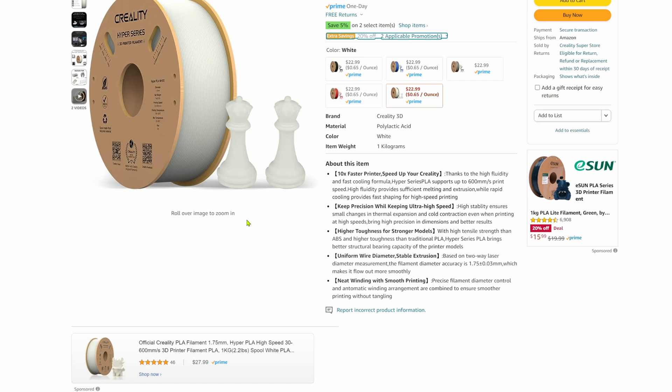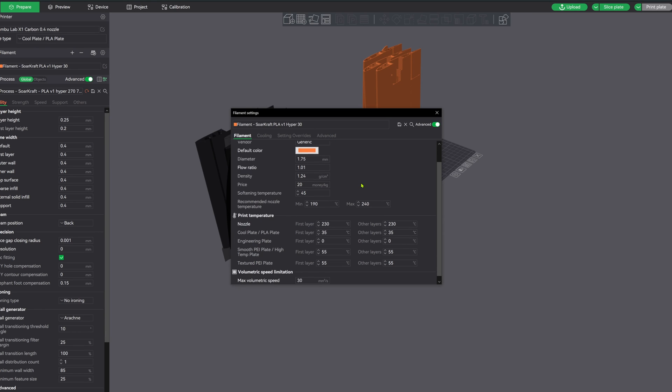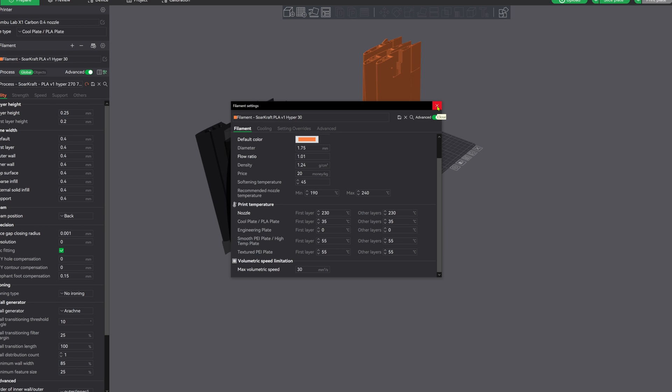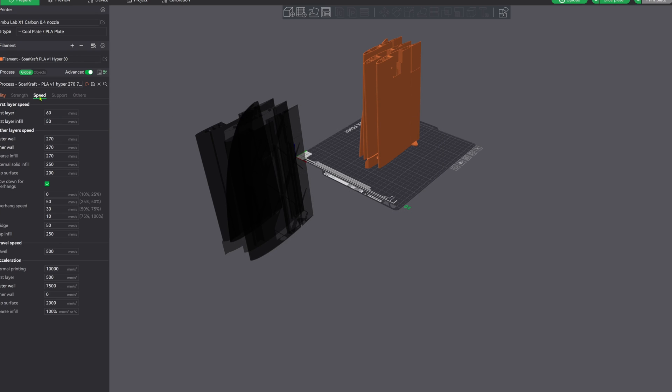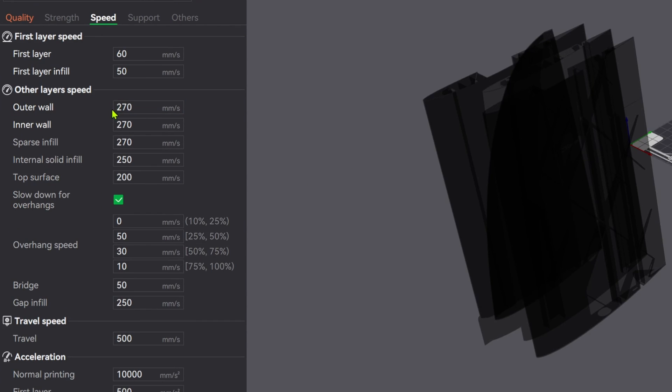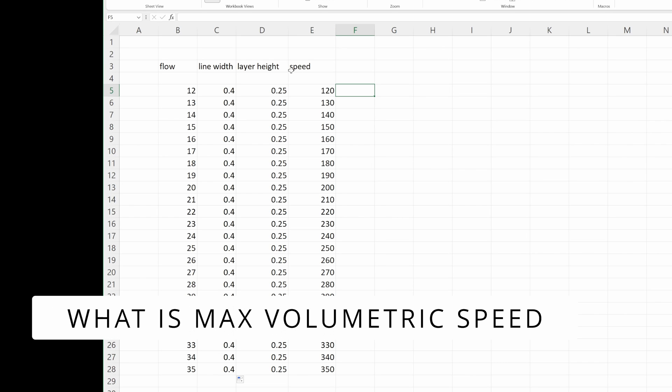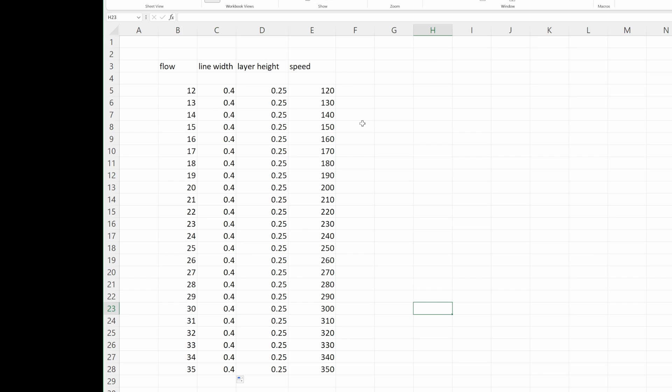Okay, so chances are that 600 millimeters per second print speed might be a little overly optimistic. Then in Bambu Lab, the true speed setting for a material is the maximum volumetric speed. The actual linear speed is secondary to this volumetric speed. There is no mention of max volumetric speed with Creality Hyper PLA. It's this maximum flow rate through the print nozzle that really sets the print speed maximum. These are the typical line width and layer heights for printing airplane parts. So at 30 millimeters cubed per second, that equates to 300 millimeters per second print speed. An easy volume divided by area to get velocity.